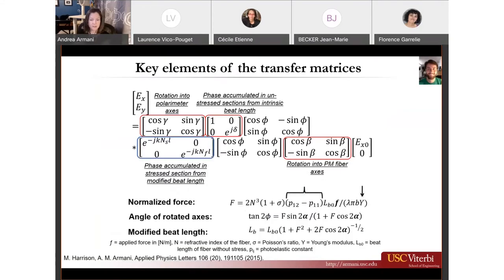This is obviously a lot of math, but seeing as the complexity of the biomaterial is very complicated, deconvolving the math suddenly becomes a signal processing challenge, which is much easier to deal with. So you set it up as a series of transfer matrices where you have the rotation into the polarization axes. You have the phase accumulated in the unstressed section from the beat length. You have the phase accumulated in the stress section, which is being modified by the fact that you're compressing over a short section. And then you also have the rotation into the polarization maintaining fiber axis, which is just an experimental artifact.